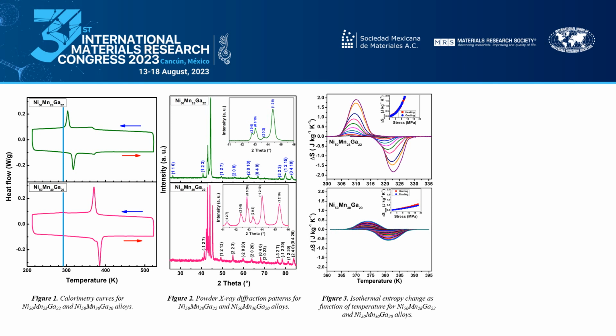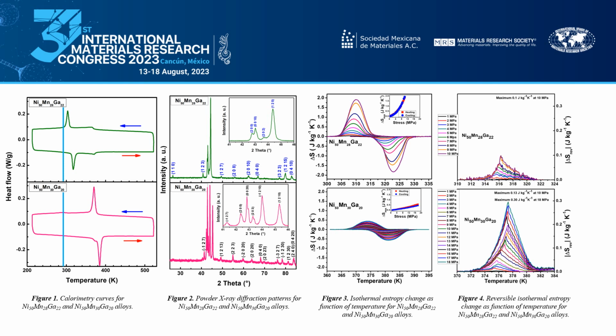For this alloy, additional values of 0.44 and 0.57 joule per kilogram Kelvin during cooling and heating were obtained when applying up to 18 megapascal. The inset in figure 3 shows that the isothermal entropy change increases as a function of the applied stress. Finally, for application in solid-state refrigeration, the most important behavior is the reversible elastocaloric effect of shape memory alloys. In this case, as can be seen in figure 4, the reversible entropy change is higher in the 7M alloy than in the 5M alloy.